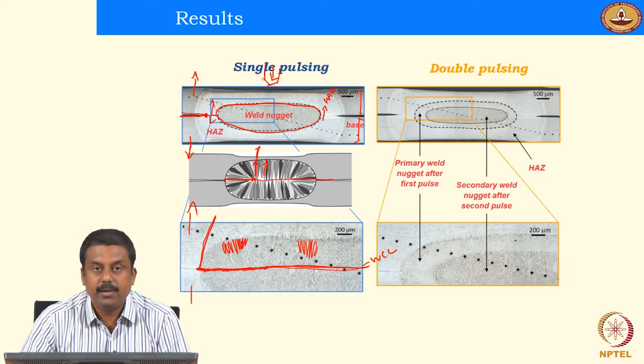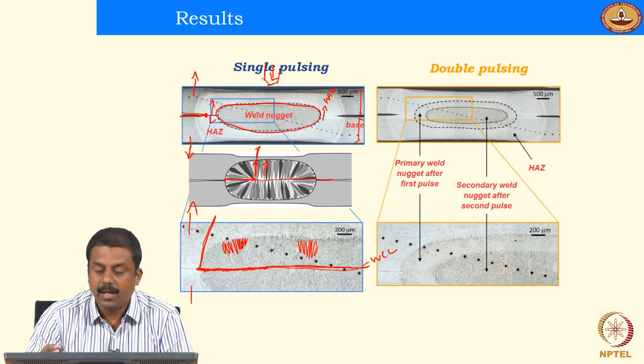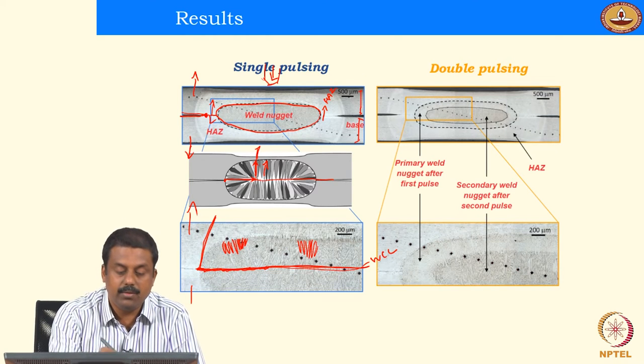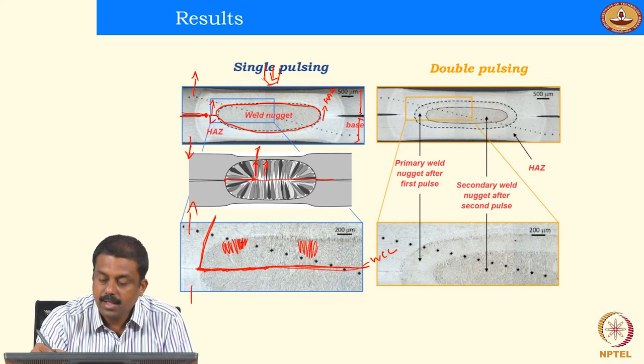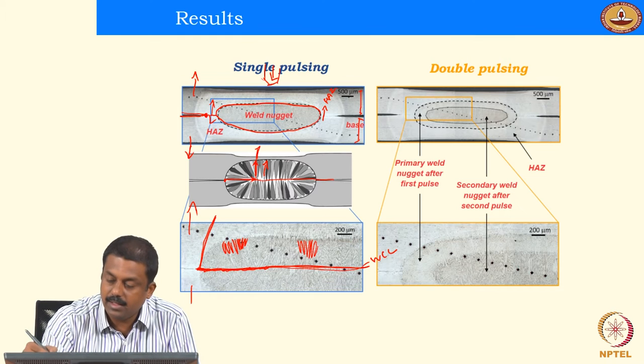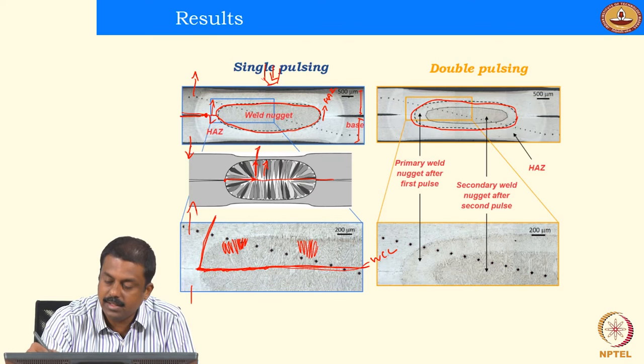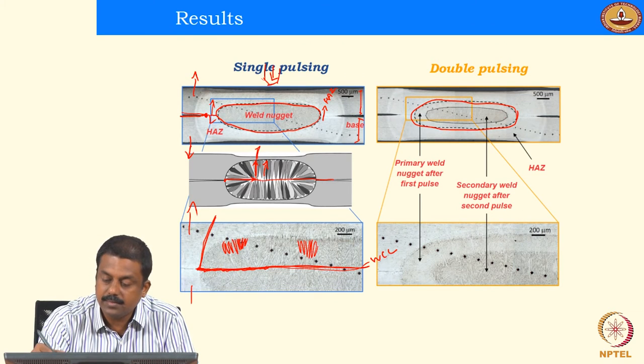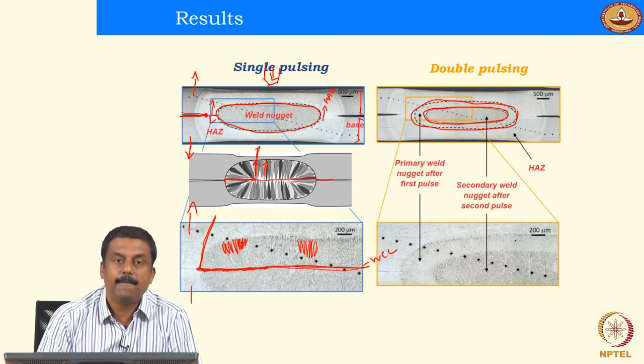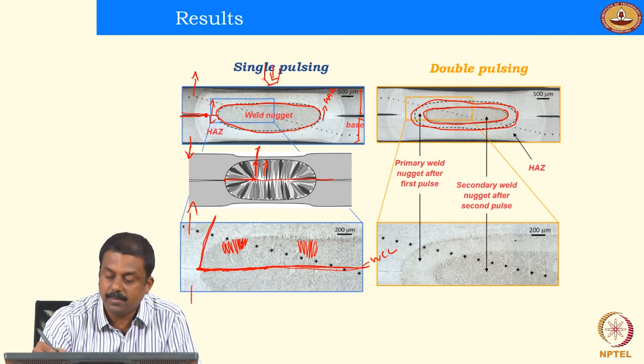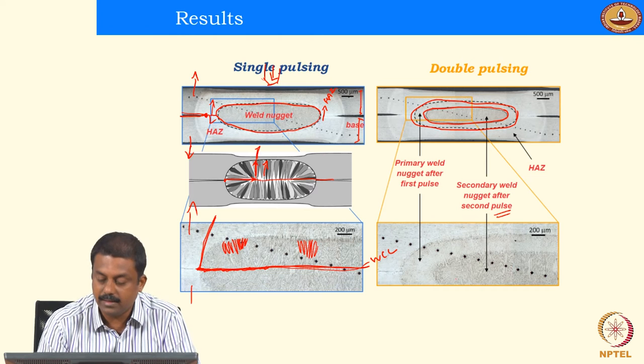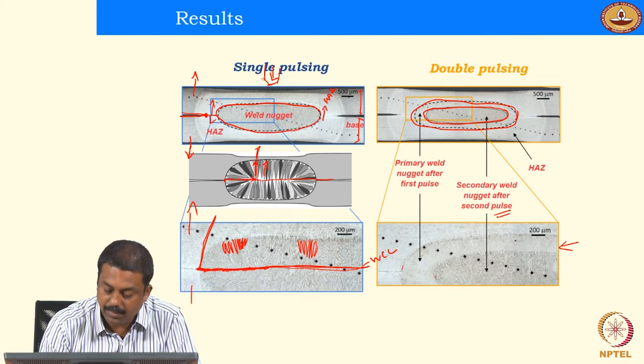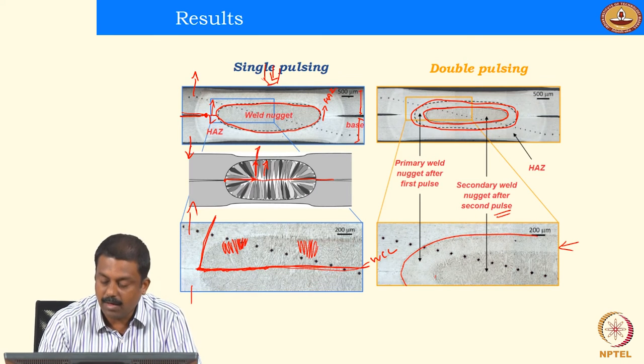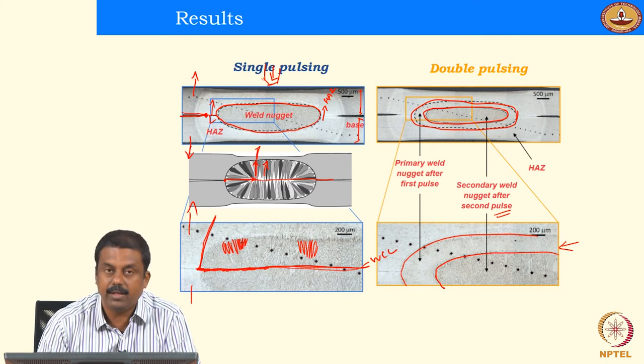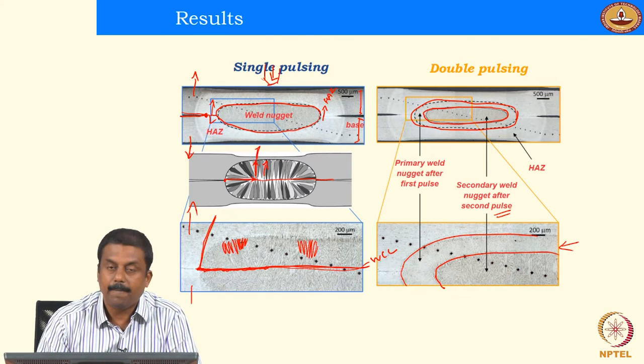In double pulsing, we have an additional current pulse given, apart from the first pulsing, which is actually used to make the weld nugget, right? This is the first pulse area. Because of the second pulse current you are given, you remelt some of the regions inside the first pulse and the nugget which is created by the first weld. So, this is the primary weld nugget, and this is the secondary weld nugget which is formed after the second pulsing. This is clearly seen from this image, where you have the primary weld nugget formed from the first pulsing, and then after applying a second pulsing, you will have a second melting of the weld center, and then you have a secondary weld nugget formed after the second pulsing.